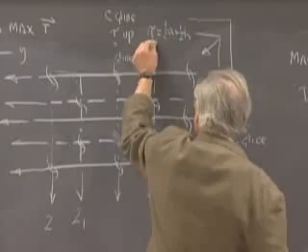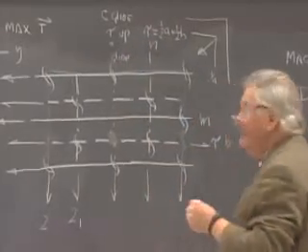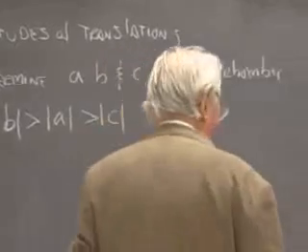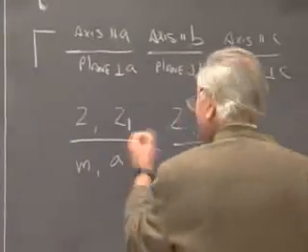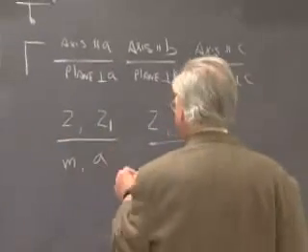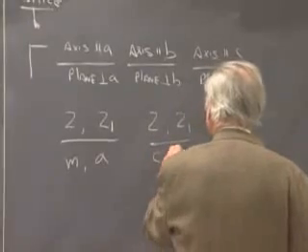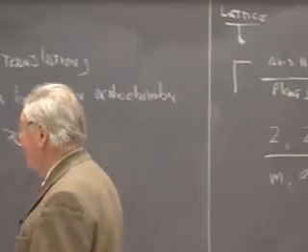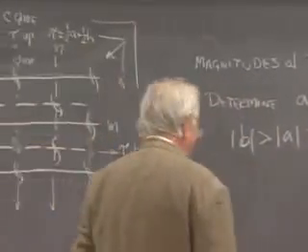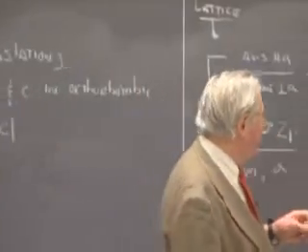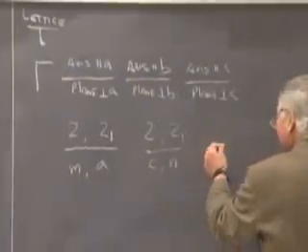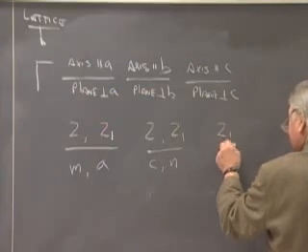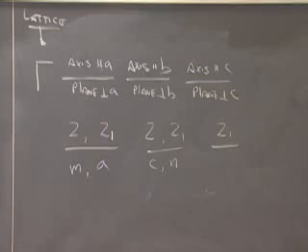And that's a diagonal glide, represented, just to confuse the innocent, by the symbol N. So two choices for axes along B, two choices for the glide plane, either C or N. And finally, mercifully, along the direction of the C axis, which is easiest to visualize because things are either along it or parallel to it, we've got only a 2 sub 1 screw axis,